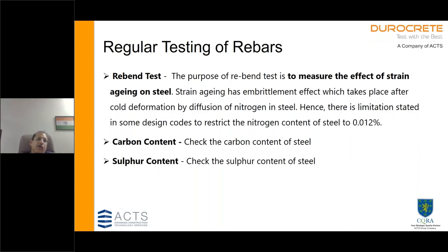Then, of course, we cannot forget testing of rebars. We all are aware of the bend test, but the rebend test measures the effect of strain aging or strain hardening. So it's in effect a kind of a durability test. Generally this test comprises of bending a bar to 135 degrees, putting it in boiling water for 30 minutes, and then again further bending it to 157 degrees and checking whether there is cracking. So basically, it is a strain aging test.